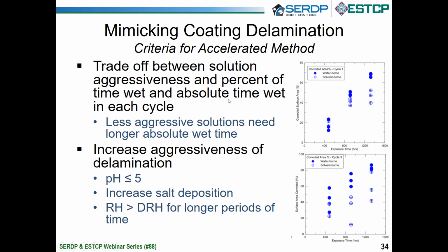So here's the interesting thing, though. If you look closely at that table, it's not simply a matter of just the time in the wet cycle. It's a matter of the solution aggressiveness. So in some of the solutions, we actually had very low wet time, but the solution was extremely aggressive. And so there's this trade-off between the aggressiveness of the salt solution on the surface and the time of absolute wetness. This is just a couple of examples, and here I'm just looking at surface delamination from two of the cycles I had mentioned before.